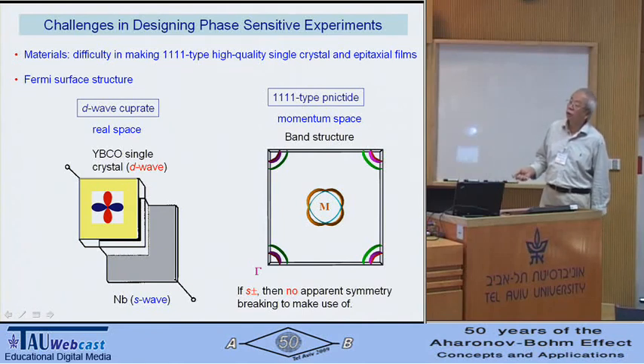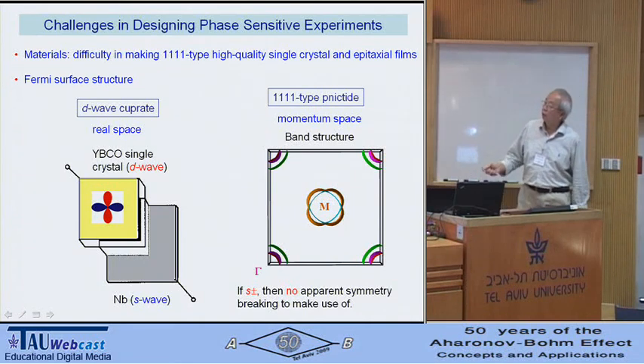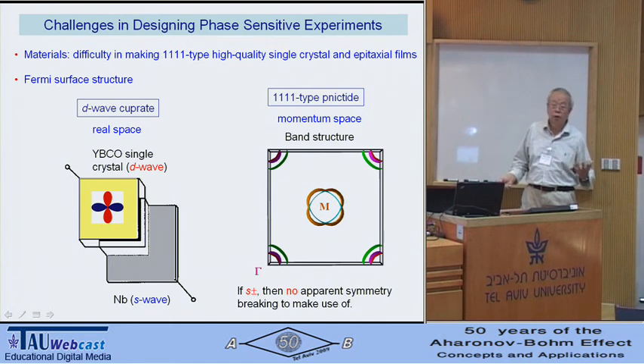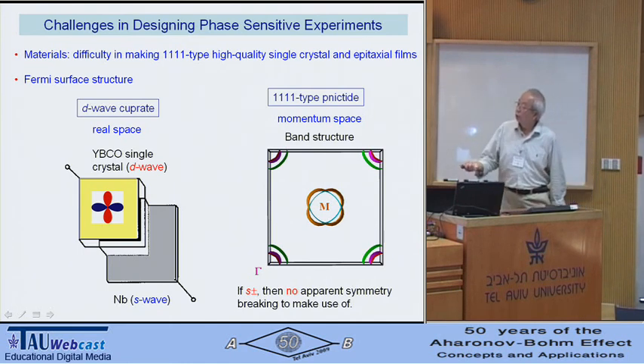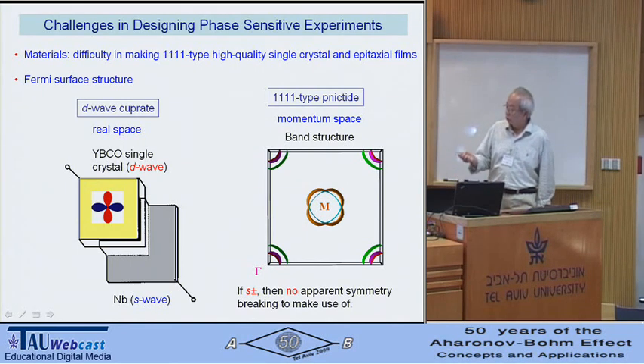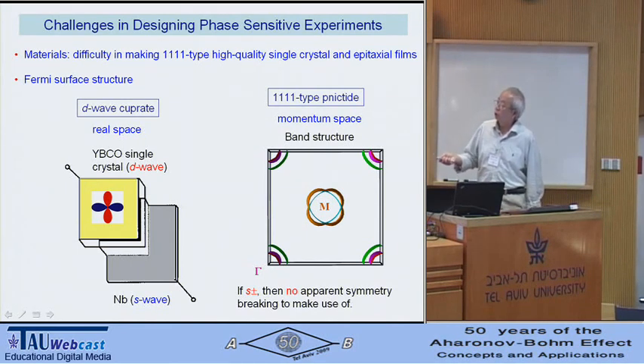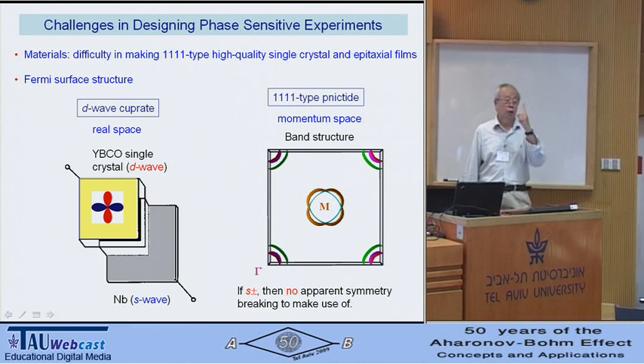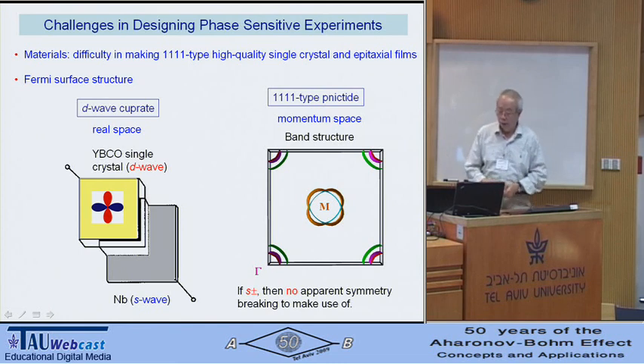Let's recall the early days when we did the D-wave experiment. For instance, if you have a D-wave material like this, and then make a corner junction using an S-wave material like niobium, which is a regular even parity S-wave superconductor. Then you go from this direction, the current goes this direction, so plus to plus. But you go the other direction, it's minus to plus. So as the supercurrent circles around this corner, what do you get? You get a sign change once. So you expect there will be a half-flux quantum here. And that's indeed the case.